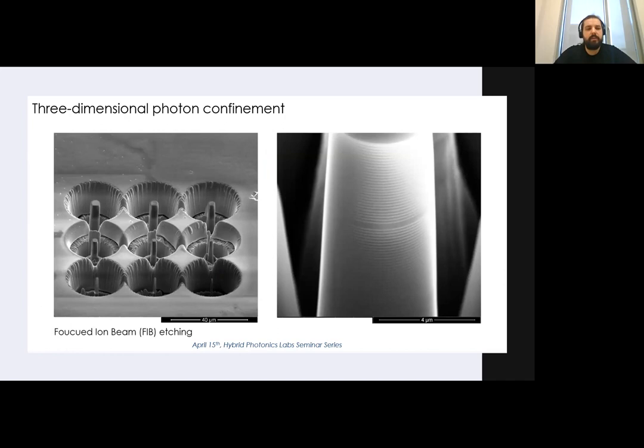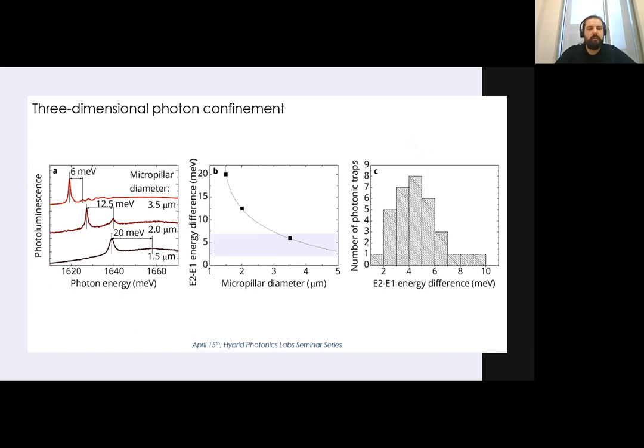So here, to compare the effective size of the photonic trap with micropillars etched from a planar microcavity, we etched nine micropillars with different diameters. Here is a close-up on one of them. If we look at the emission from the micropillars, we can observe different distances between the modes. And now we can compare it with typical spectra from photonic traps. We checked 33 photonic traps, and the typical effective size of the microcavities is similar to the case of a micropillar with a diameter